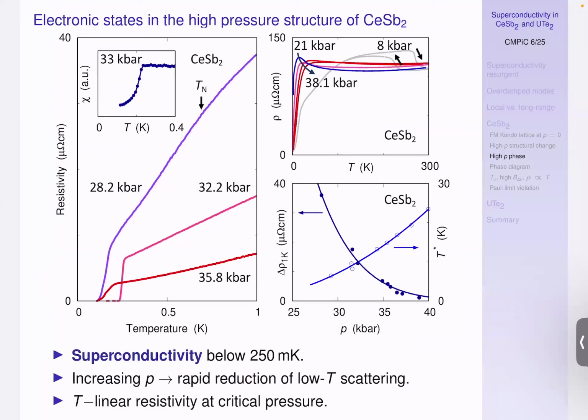This is basically how 90% of the research in my group works. There's a phase diagram, here's an interesting region, let's have a look. It was a little tricky because it's just outside the range, on the limit of the range of these cylinder cells, so Oliver Spire, who did these early measurements, used an anvil cell. What you find is, first of all, you can see this kink in the resistivity, which is the magnetic transition. At 28 kilobar it's still there, at 32 kilobar it's gone, and at low temperatures cerium antimony 2 goes superconducting. So we found one more of these cerium-based high pressure superconductors.